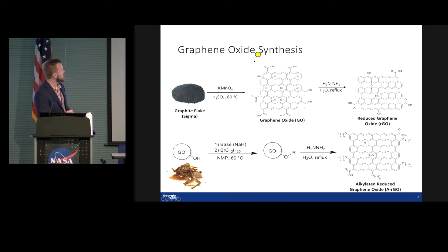This product is actually water soluble. It's soluble in a lot of other solvents as well. But the point being is that we can generally process it, do things with it, and then reduce it down to graphene. And so we get this nice, conductive, mostly planar structure, but it does have a few defects remaining from this graphene oxide stage.